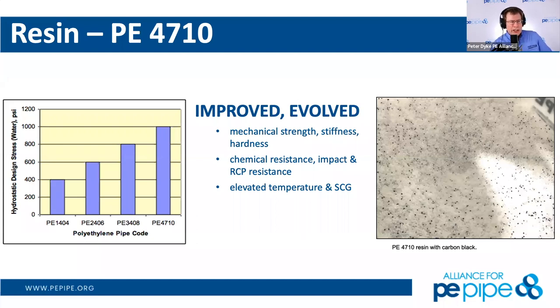But we're now looking at the fourth generation resin, and we have those little black things in there. That's the black master batch that gives polyethylene its indefinite outdoor life under pressure. So it's not like PVC. We're not going to degrade over time. Now, that gray pipe I showed you on that one video, that will degrade in the presence of sun after 36 months. But prior to then, it's okay. But black pipe, no problem.